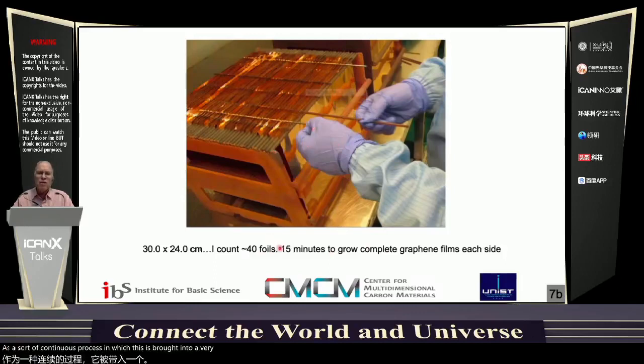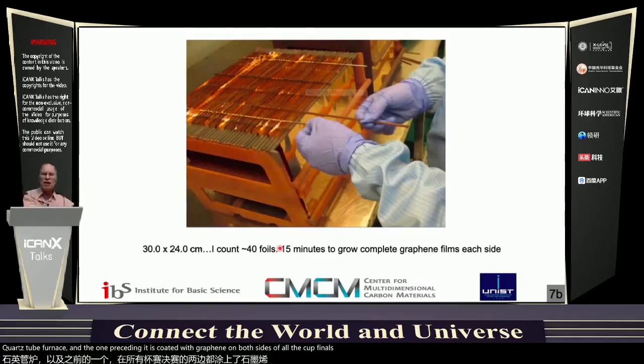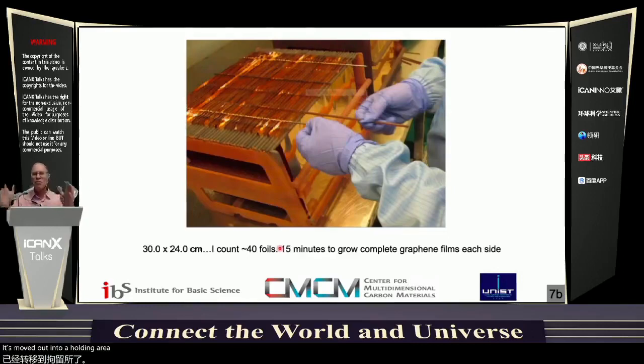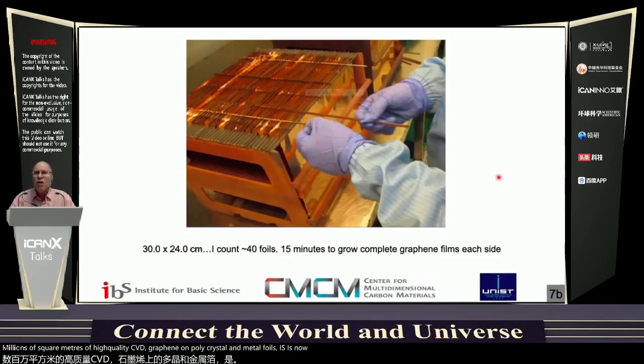a very large quartz tube furnace, and the one preceding it is coated with graphene on both sides of all the copper foils. It's moved out into a holding area, pump purge the growth area, and then you keep it hot, and then introduce growth species like methane and hydrogen. And so millions of square meters of high quality CVD graphene on polycrystalline metal foils is now achieved around the world.